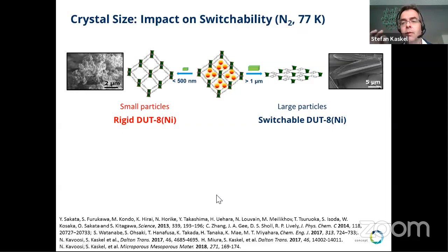It has been shown that crystal size has a pronounced impact on switchability and adsorption isotherms. And again, we study this model material here, which we call DUT-8. We observe that upon desolvation of the network, if the particles are below 500 nanometers, the network does not form the contracted phase, the CP phase. Only if the crystals are larger than 1 micron do they transform into the CP phase. So there's a pronounced effect of crystallite size on switchability.